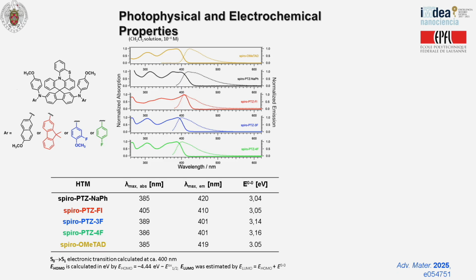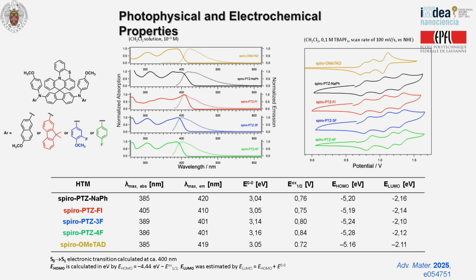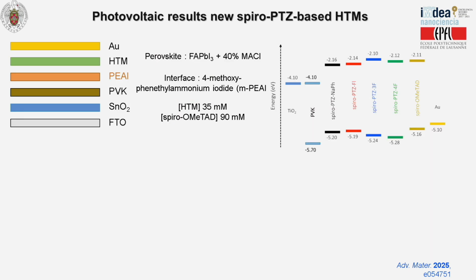So in our system, it turned out to be much more competitive, and you can see the absorption and emission spectra. And again, the interest was in these systems having the larger pi system. And we also determined the electrochemical properties, and with this it was also possible to determine the electrochemical band gap. So this is interesting for these molecules: the very good alignment, okay, between the titanium oxide, the perovskite, the typical perovskite we use in this case, and also the metal electrode.